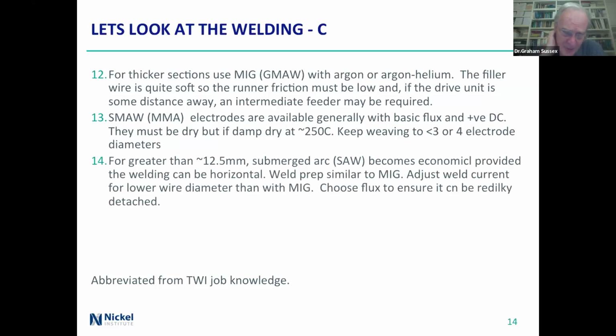And if you're looking at something more than about 12 or 12.5 millimeters, then submerged arc, yep, economical, provided you can make sure the welding is horizontal, because otherwise things tend to flow around a bit.